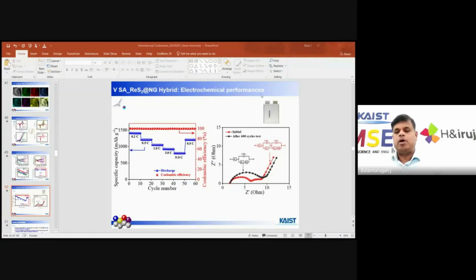We also make the pouch cell. After making the pouch cell, we do the durability and rate performance study. You can see different current densities, and we get the higher coulombic efficiency. And we also do the before and after performances in the pouch cell. After 600 cycles, we get a single redox peak, and before it was two. So based on the intercalation of some lithium, we get the single RS and RCT values.